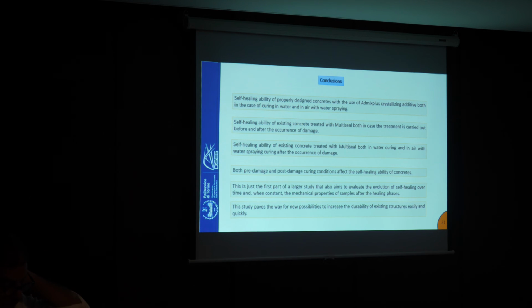Okay. So you have something like concrete, similar to concrete. No, it reacts with something present already in concrete, in cementitious material. Because the CH is produced by the hydration of C3S and C2S, you have this material prompt to react at every age of the concrete. So it can react in every condition, you need only humidity.